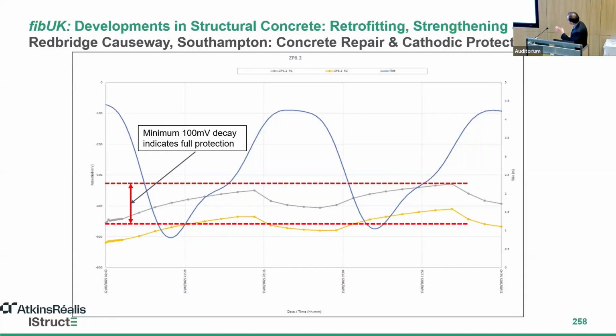In terms of monitoring, the key point about a CP system is maintenance and monitoring. You cannot just leave the system running, because if the potential exceeds a certain limit, you start to damage the steel rather than doing any good. This is a typical monitoring graph for the CP system for one of the zones. The test that we use in accordance with BS 12696 is the depolarization test. Effectively, we switch off the system for a period, typically 24 hours, and we monitor the potential decay of the reinforcement over that period. And there is a limit that we need to satisfy. It's a practical and theoretical limit that shows the system is operating properly and the steel is fully protected.